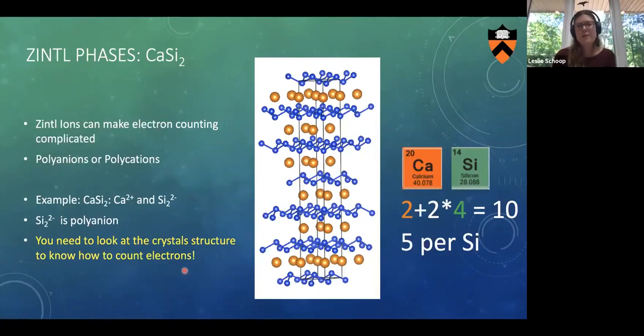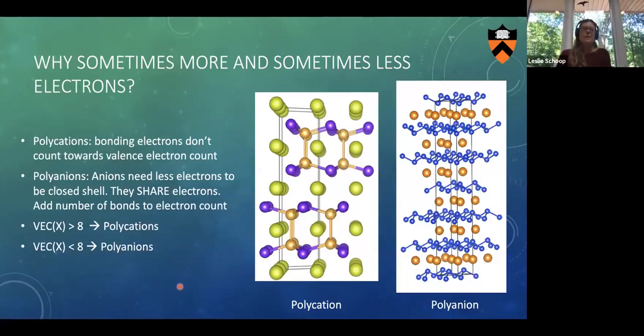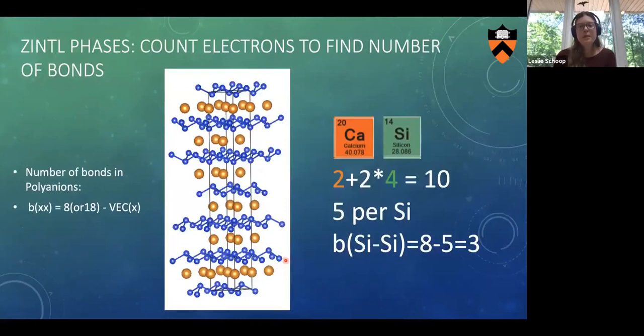And so Zintl phases have been established a long time ago, and they differentiate between polycations and polyanions, depending on whether you have more than 8 or 18 valence electrons or less, what kind of structure you form to stabilize the electron count and still have a semiconducting system. And there's a simple rule for how you can check if your Zintl phase is charge balanced. It's a kind of bond formula. It says that you have a bond order that you can calculate by subtracting the valence electron count of your X atom, which is whatever forms the polyanionic or polycationic structure, from 8 or 18.